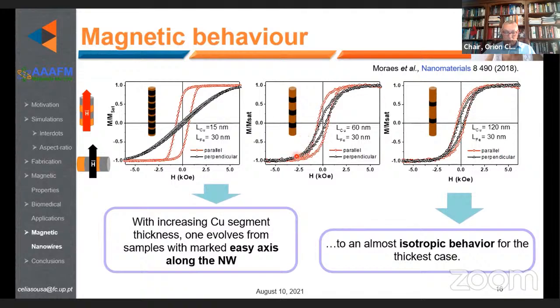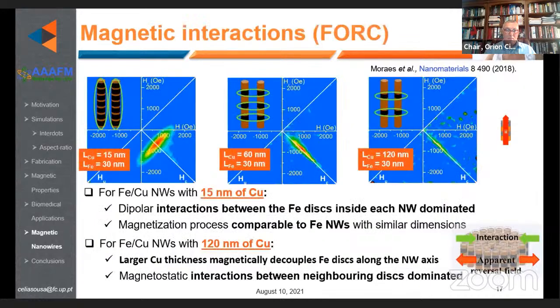Regarding the magnetic behavior, we can see that by increasing the copper segment thickness between the iron nanodiscs, one evolves from samples with a marked easy axis, as we can see here, dominated by a shape anisotropy, to an almost isotropic behavior when we increase the separation between the iron layers.